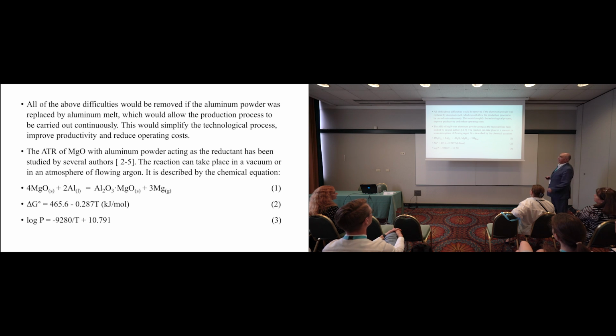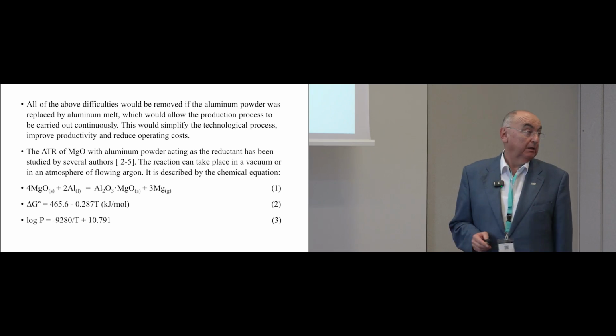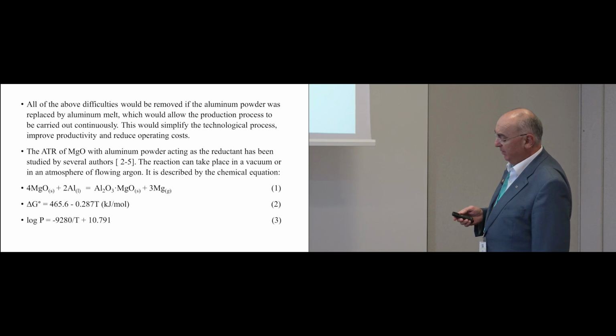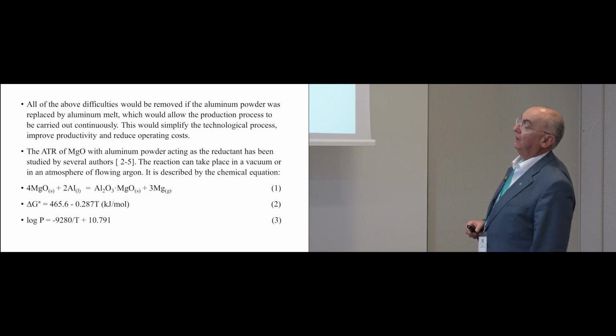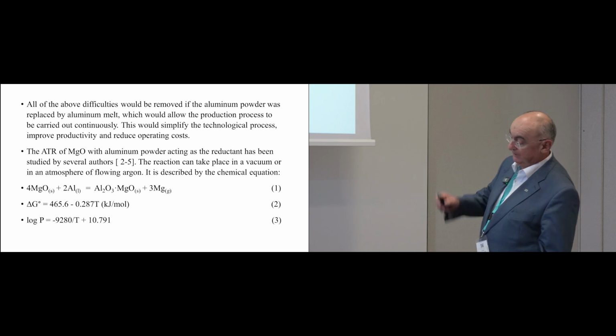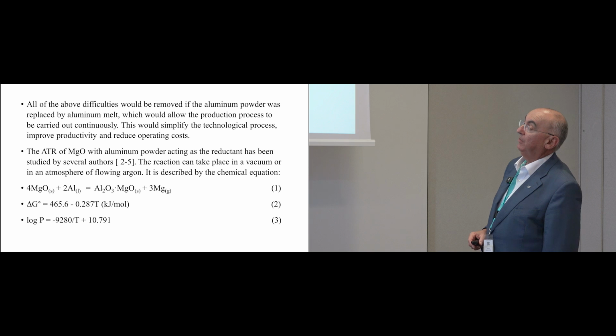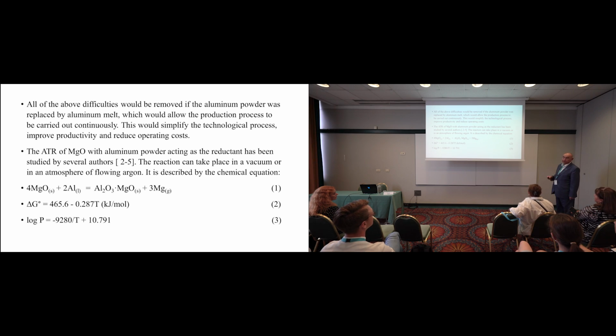It looks very simple, but the problem is that this reaction occurs at a pretty high temperature, roughly around or above 1,400 degrees, mostly in vacuum. And usually they are using aluminum powder. Of course, I put it here that aluminum is liquid, but it's liquid only during the reaction. As a raw material, it's a fine powder.